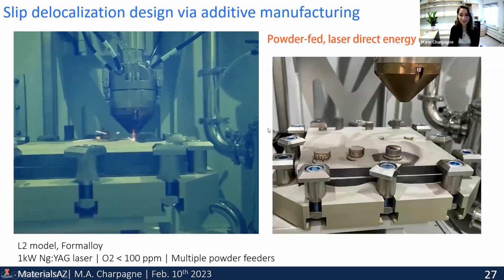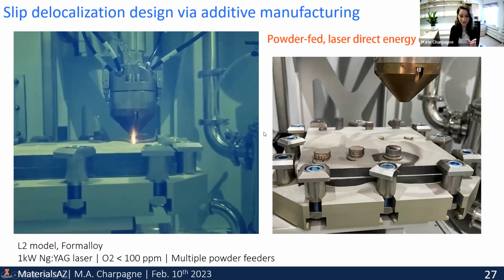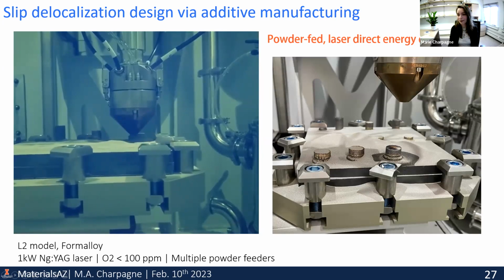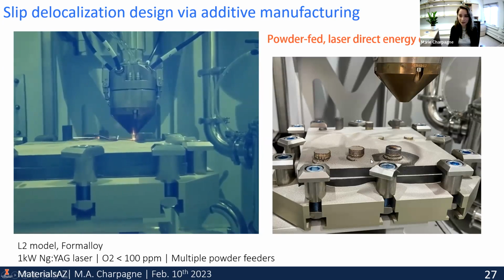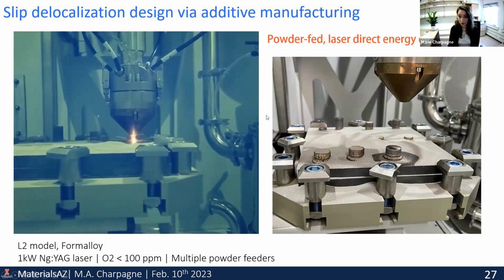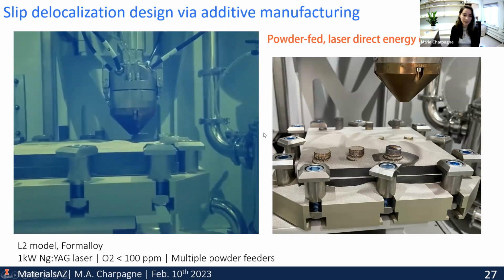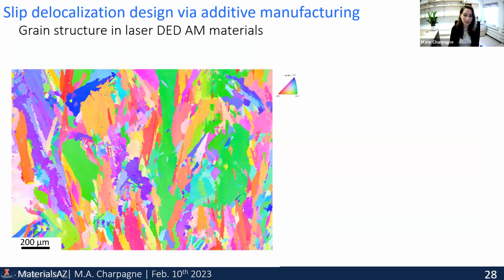So this is very recent. We're going to look at the DIC maps of these materials very soon. And now we're just playing around and finding what printing parameters give the best microstructures in those materials. We installed our printer like 2 weeks ago, so this is very recent, but we're in the process of characterizing the microstructures. And what we have so far is very long, elongated grains that are full of different orientations. And also, of course, you can imagine this one will have high lattice rotations. They have very intricate structures, but the main thing I want to comment on here is that there are no twins. So this is pretty good news.